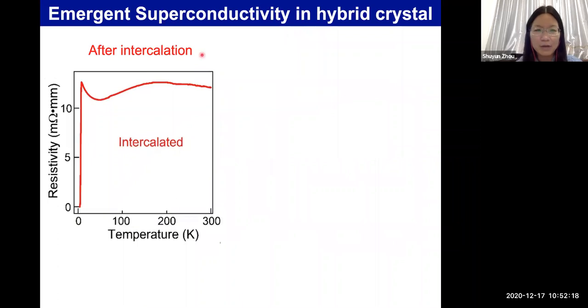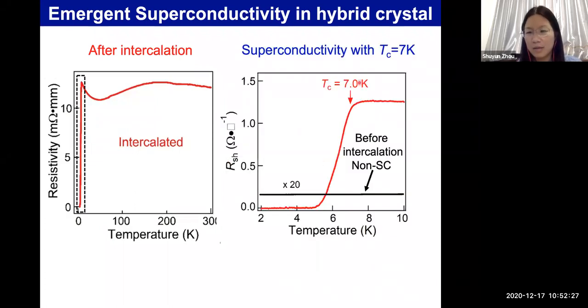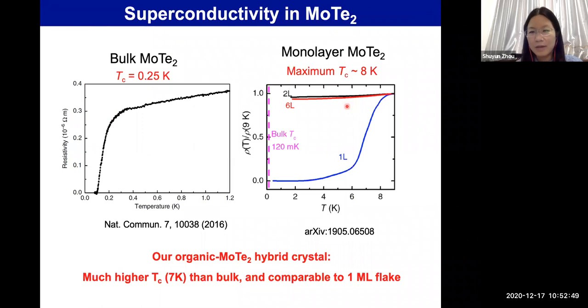Now we also see that after this intercalation, the resistivity drops to 0 at low temperature. If we zoom in on this low temperature region, we'll see that before intercalation, the sample has very low resistivity, however, it is not 0. After intercalation, we can reach 0 resistivity with a transition temperature of 7 Kelvin. So how is this 7 Kelvin superconducting transition compared to the bulk and monolayer flake? Here are the reported results for bulk molybdenum ditelluride. It has a transition temperature of 0.25 Kelvin. And for monolayer flake, the maximum Tc is 8 Kelvin. So our intercalated sample shows a similar Tc to the monolayer flake, and the Tc is much higher than the bulk sample.